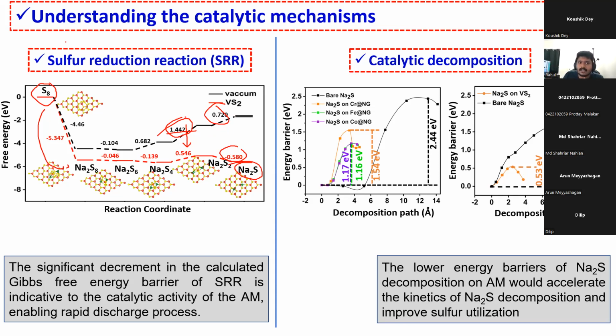Now, I have talked everything about the discharge. We have the shuttle effect, we found the binding energy calculations, and then we went to the sulfur reduction, how the polysulfides are getting converted. Now we have Na2S. Now this Na2S is the final discharge product. It should go back to its normal state during charging. Basically, the Na2S should break and Na should diffuse and go back. So for this, we should have a sodium and sulfur bond breaking. Only after breaking this bond, the sodium ions can go.